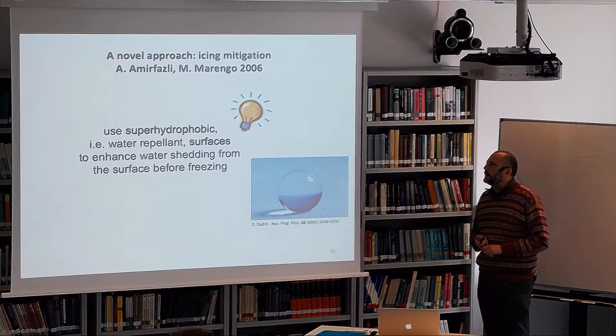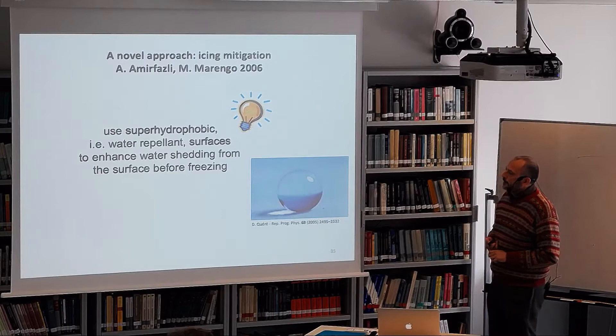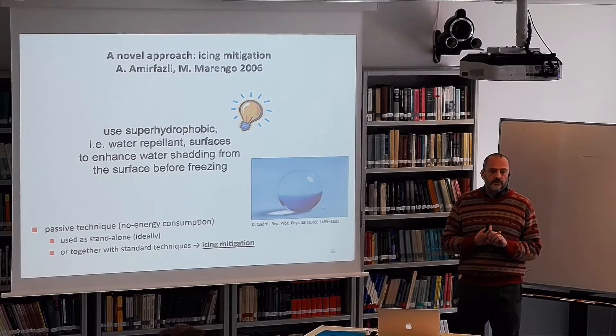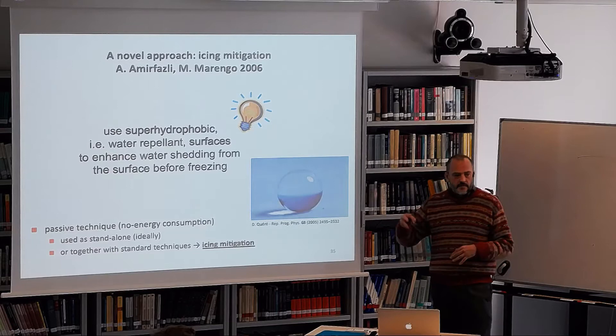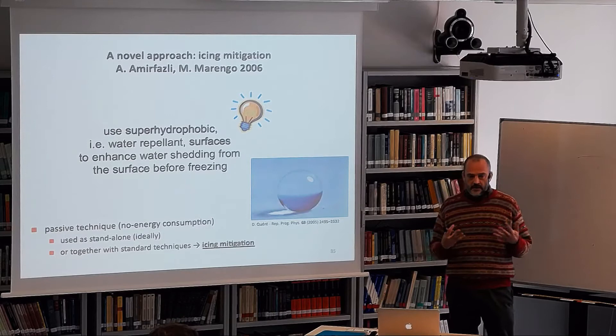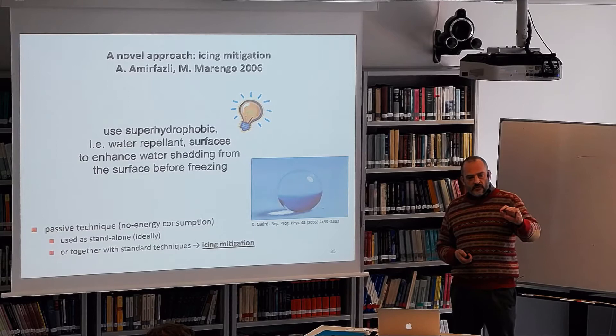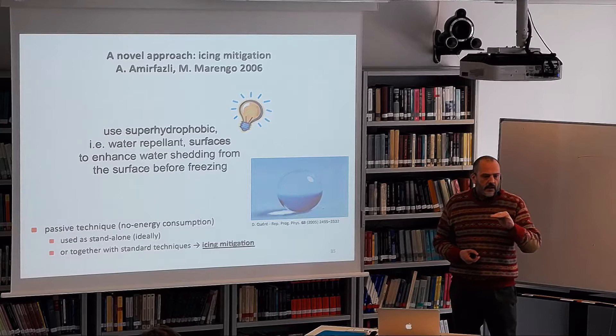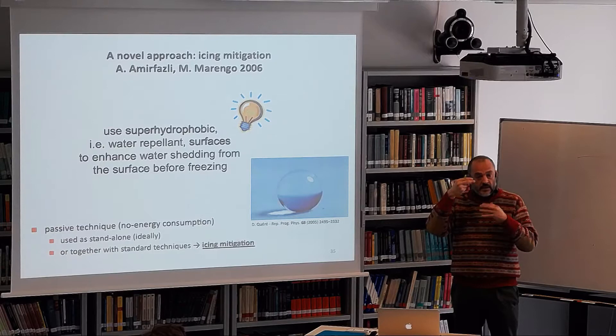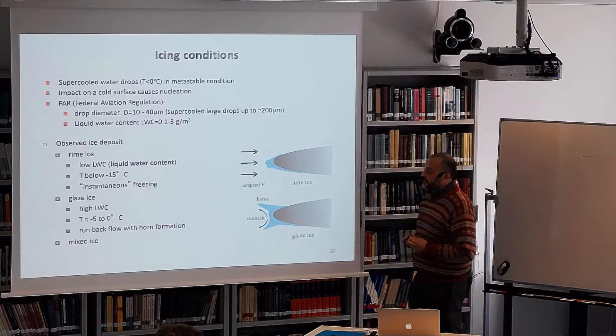In 2006, together with Professor A. Amirfazli, we proposed the icing mitigation technique. The idea is to reduce energy consumption — in aeronautics, to avoid ice formation, surfaces are normally heated to 60°C, which is a huge energy cost. The idea: use super-hydrophobic surfaces so that at only 5°C instead of 60°C, you avoid ice formation. Keeping wings at 5°C instead of 60°C represents a very large energy saving.